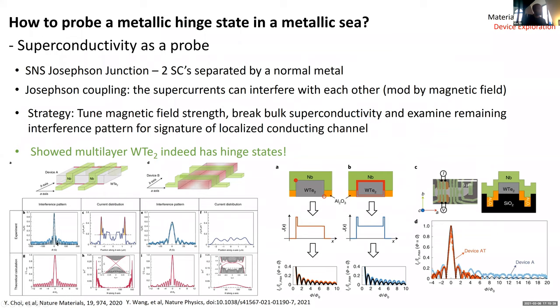If I take the critical field as the field at which the SQUID oscillation is lost, because even that superconductivity is suppressed, then it persisted up to, I think in our best device, like 350 Gauss. So it just kept going for a little way, almost twice as far as in this figure here. But is that also limited by the kind of superconductor that you use to proximitize? For sure, yeah. In no way is this an optimized engineered device, absolutely. If you used a different superconductor, you could definitely tune that. We use niobium, type 2, which has some penetration.